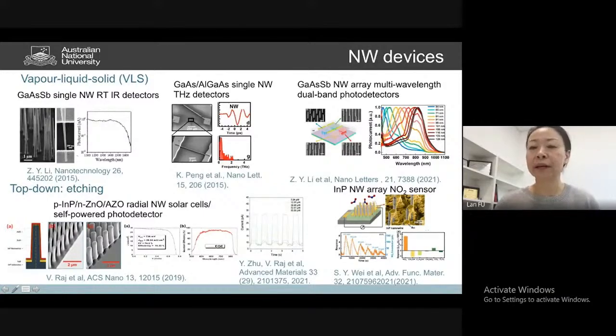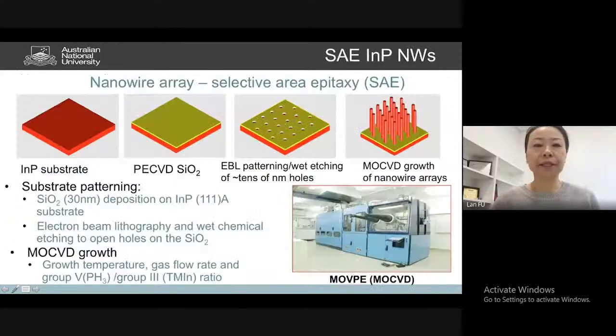Again, we've also demonstrated making them using top-down etched indium phosphide to make a chemiresistive sensor, which is highly sensitive for nitrogen dioxide gas sensing. Nitrogen dioxide we know is a very well-known air pollutant coming from your petrol-based car. And I know that in India there are lots of cars on the street, so the pollution is a problem. So those kinds of nanowire arrays can be really, really sensitive to measure low-level and high-level nitrogen dioxide concentration in the air. So it's a lot of opportunities over there.